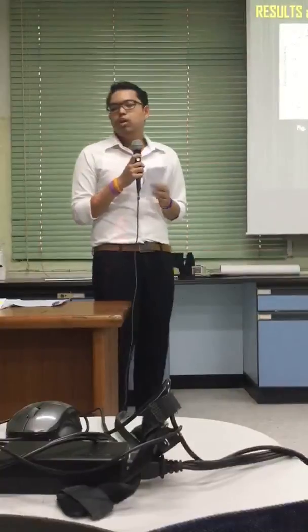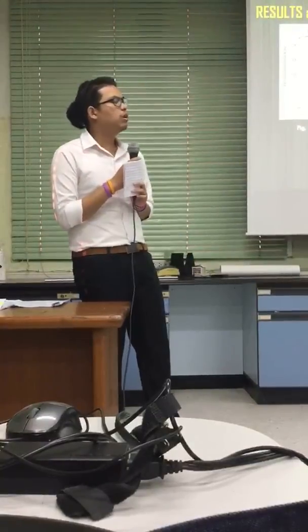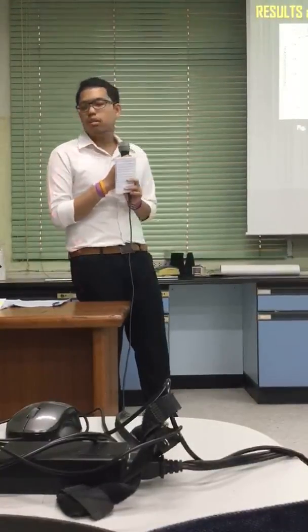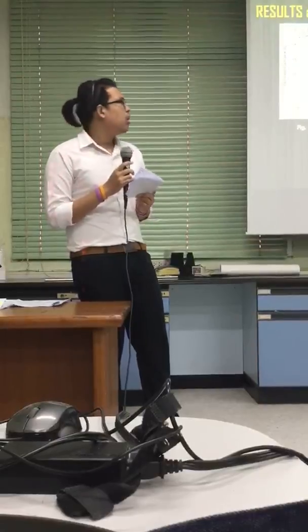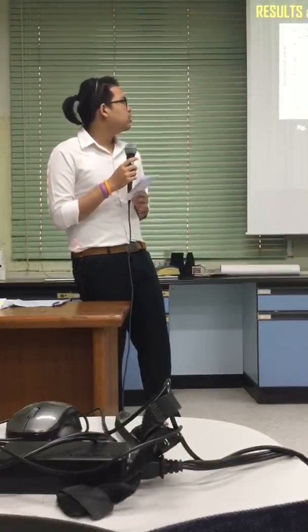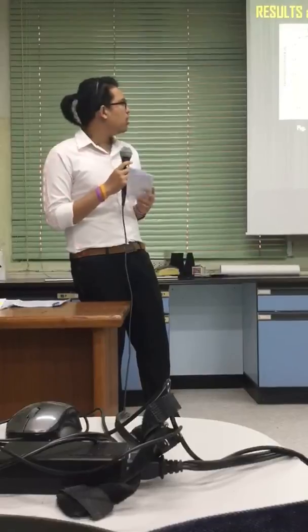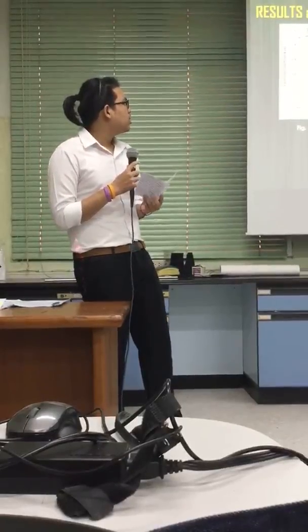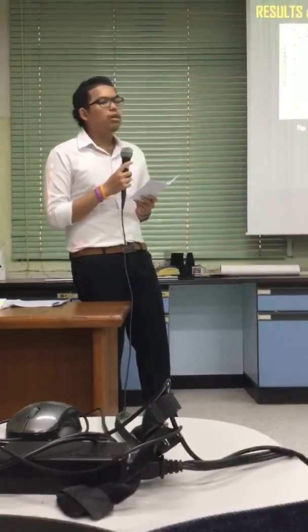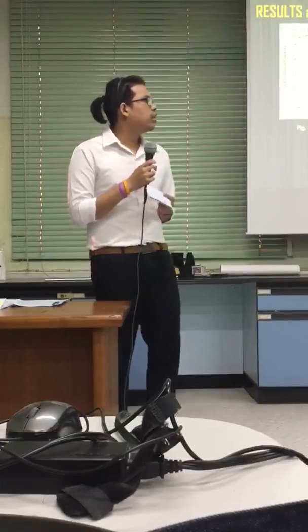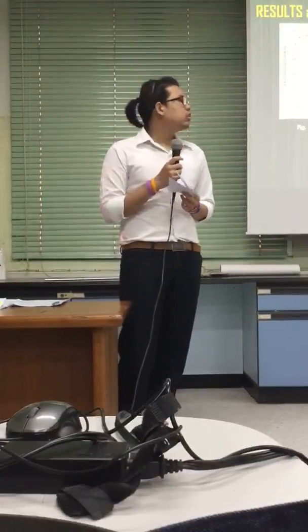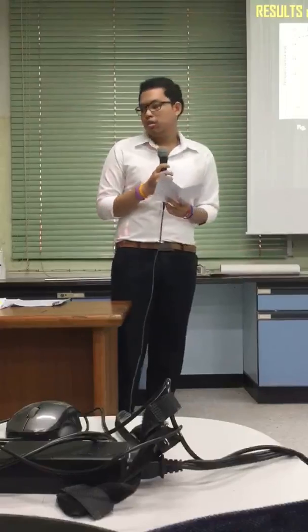And about extinction coefficient, use Cauchy model shown in Figure 16b. Extinction coefficient is decreased with higher wavelength at 400 to 800. Therefore, the sample is a transparent material.